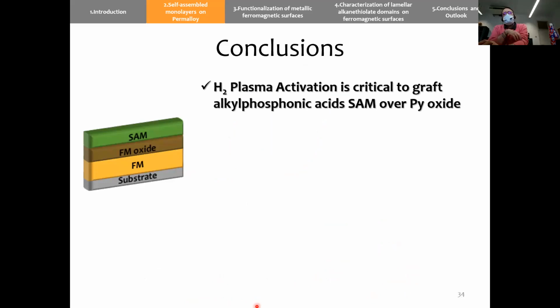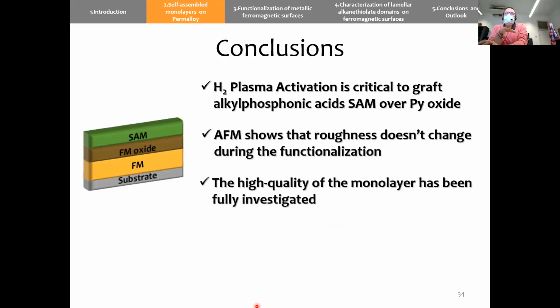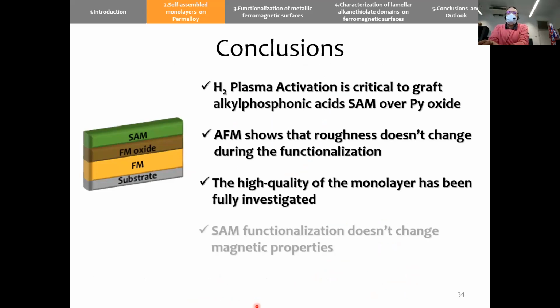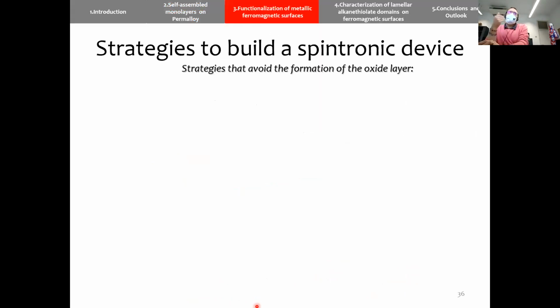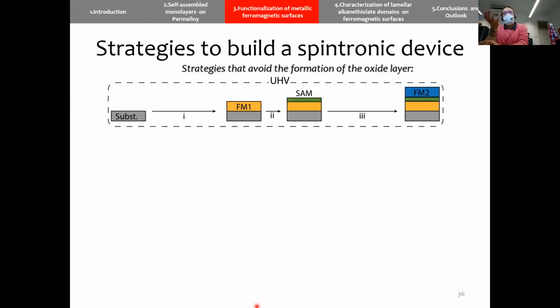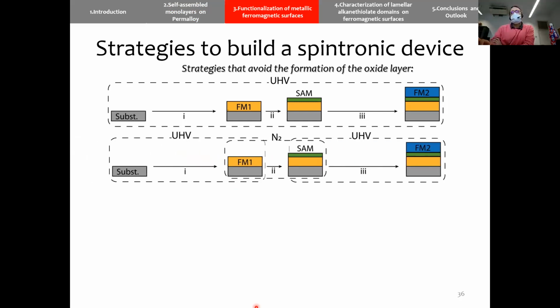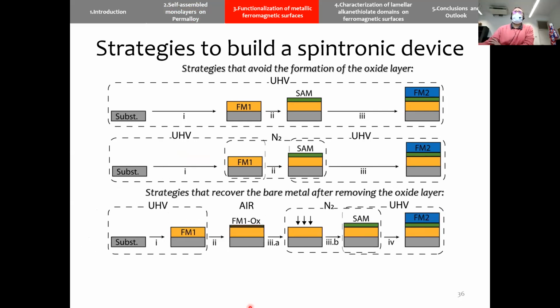And so for this part, we can see that this activation is critical. The FM surface is smooth, the high quality monolayer has been fully formed, and we don't observe any change in the magnetic properties. Then, in order to graft it on the metallic part, there are different strategies that can be used.